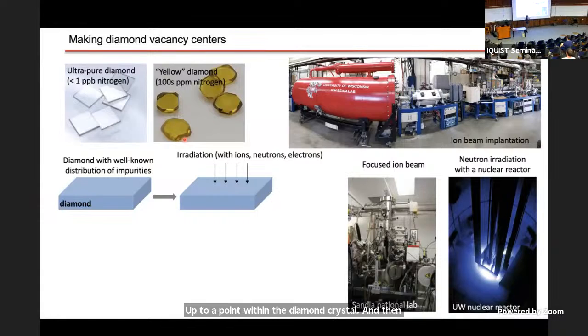You can see the Cherenkov radiation at UW-Madison. We've also stuck diamonds inside this nuclear reactor to generate vacancies. After that, you have vacancies, which means that many carbon atoms are being knocked off. Some of them are randomly close to a substitutional nitrogen, but not all are, right? So your crystal is pretty damaged.